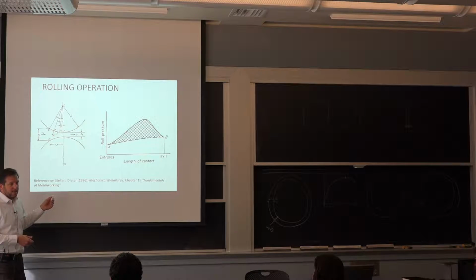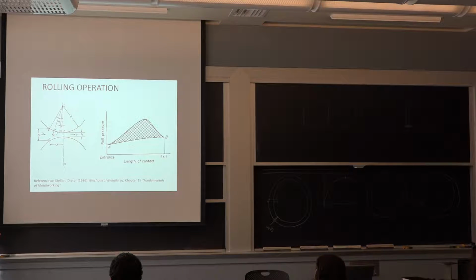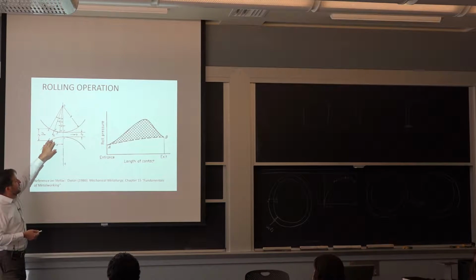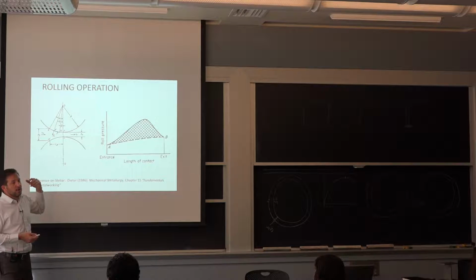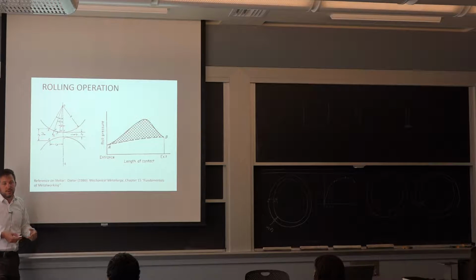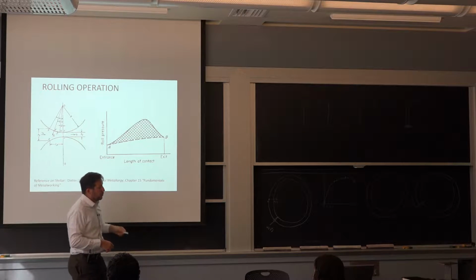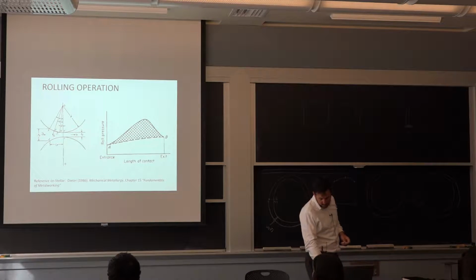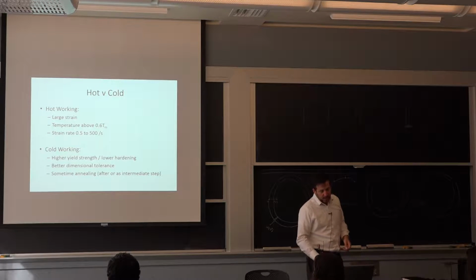In the case of rolling, we use the friction between the roll and the product to actually drive the metal through. So there's been a lot of study done in terms of, first of all, making sure that you don't stick between the roll and the product, but also that in this process you maintain everything under a compression pressure as opposed to tension, and that is to avoid the problem of cracking during forming. So you want things to be in compression. It's not a problem with rolling. It can be a problem with other processes that we're going to see.